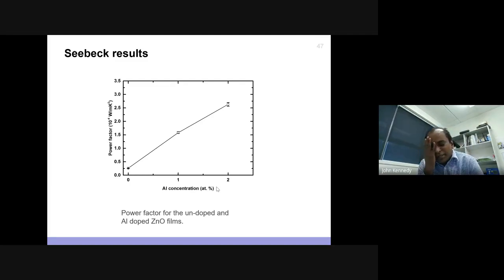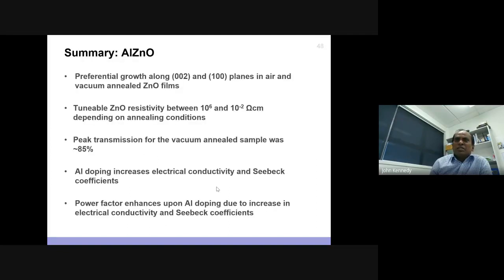The reason why we picked zinc oxide is it's used in industrial applications because it's a cheap material, it's an oxide, and you can easily make thin films by sol-gel, any chemical processing technique, or any thin film techniques. We wanted to see how you manipulate the power factor so that this could be used as a transparent thermoelectric. The efficiency is very low, and that's the reason why zinc oxide is not successfully commercialized. If you dope too much, it becomes too highly conductive, the carrier concentration goes too high, which means you will lose the Seebeck. So we were able to tune it to an optimal range.